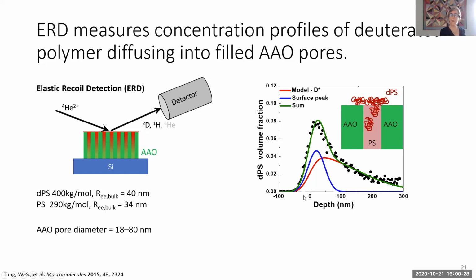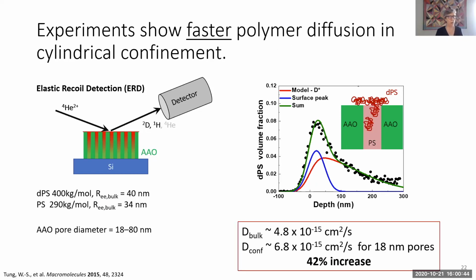The blue curve says there's a little bit of deuterated styrene that stays on the surface. And then the red curve is the concentration profile of the polystyrene that's able to diffuse into these pores. And again, without belaboring the point, I'll just show you one data set. And it clearly shows that the polymer diffusion is faster when the polymer is going into a cylindrical pore.